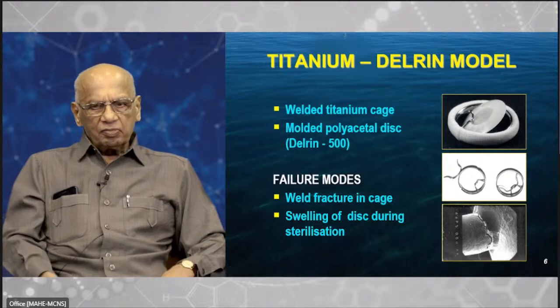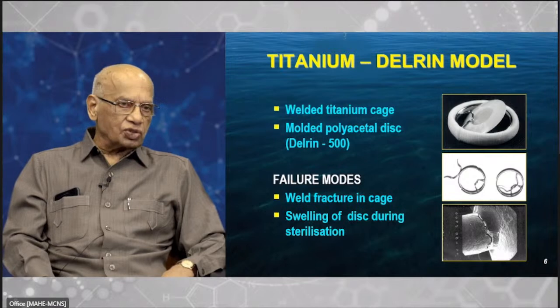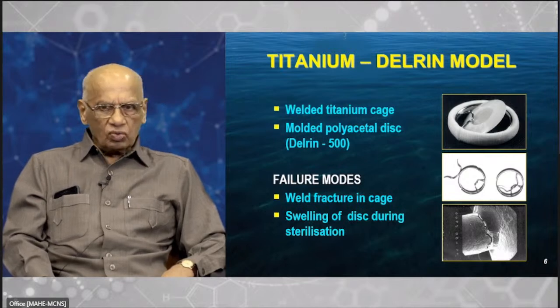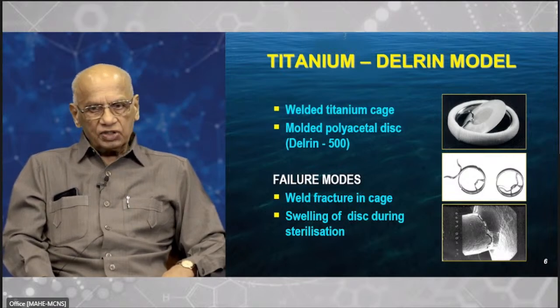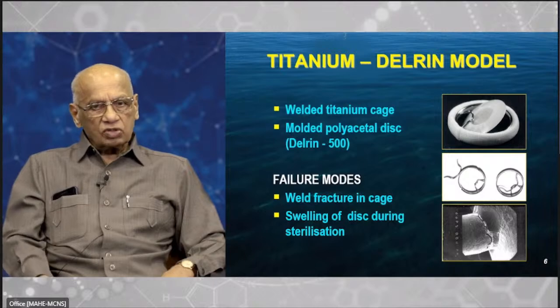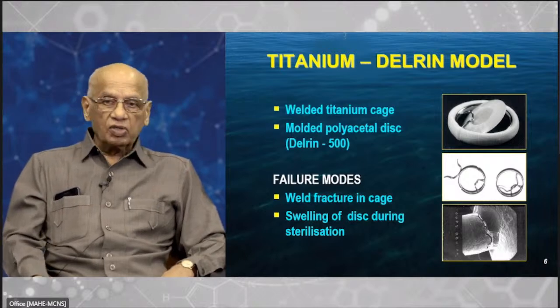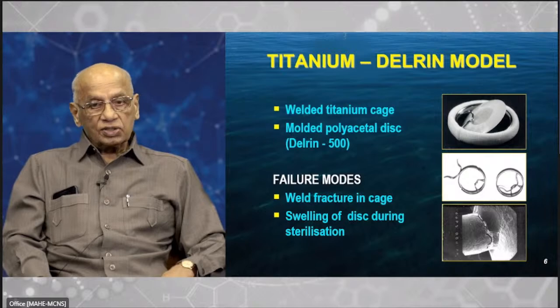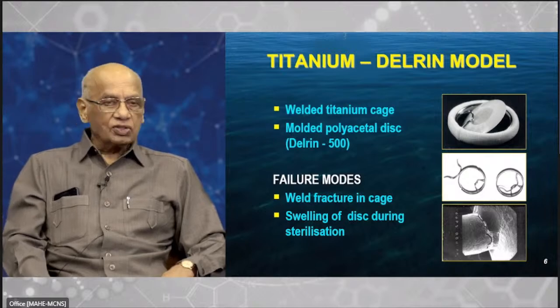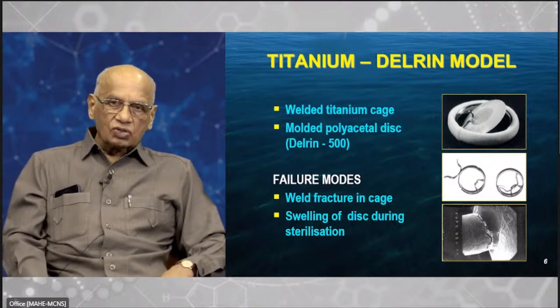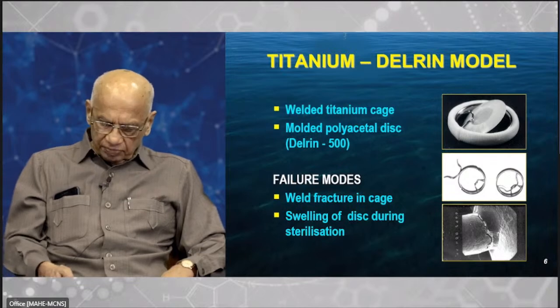And they told us this happened because in the electron beam welding chamber, there is a trace of oxygen. That led to weld embrittlement. That's why it fractured. And the lesson we got was we should not use welded components in the bloodstream. That's not safe. That was the conclusion. So we had to change the model, and we moved to the next.